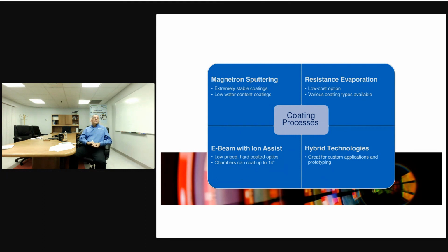I would say the only downside of magnetron sputtering is you have to consider your surfaces. If you're looking for a really pristine surface, magnetron sputtering can sometimes add stress to a surface of an optical substrate. There's ways of getting around that. You can have a robust ratio of the size and the thickness. You can make a robust substrate so the substrate doesn't bend and twist. You can also put compensating layers on the backside. So if your backside was going to be an AR and your front side was a multi-layered dichroic, you can even out the layer count so the substrate doesn't bend and twist. But overall, a very good